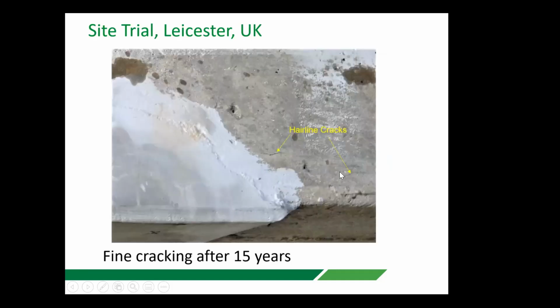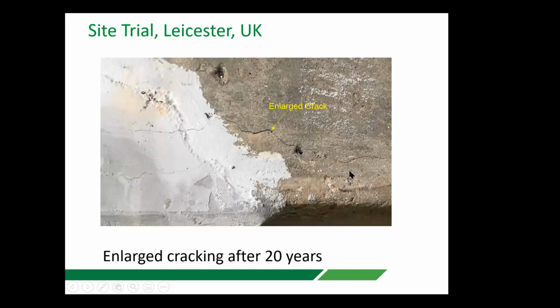Looking at it at 15 years, we could see that there was a sort of hairline crack that was just beginning to develop. This is the one patch area, the other one is over here. So the crack was actually developing. So at that time, at about 15 years, we were not producing enough current to control the corrosion in that region. And that eventually became thicker at 20 years. And we could actually see that very clearly and moved into the patch repair. So up to 15 years, we could claim that we were able to maintain the patch repair in a good condition that did not require anything further. Now we're in a position where we need to go back and do something to that patch repair.